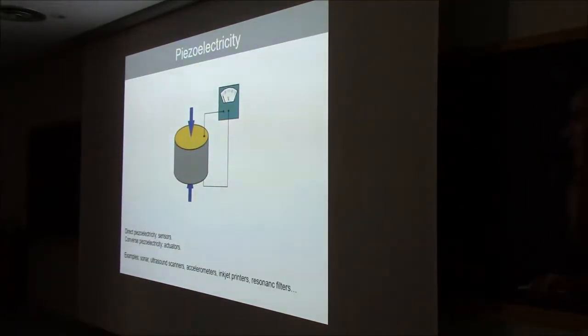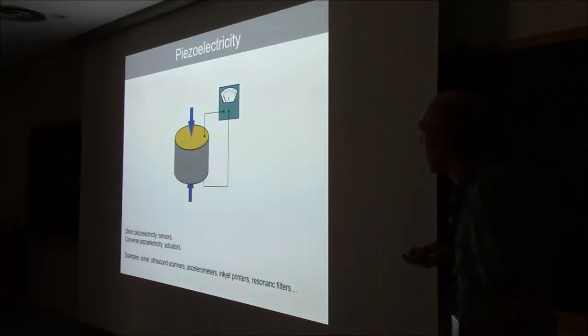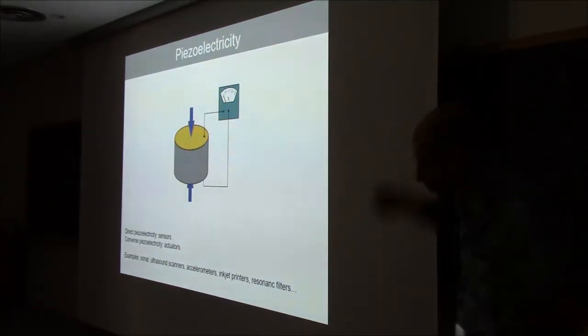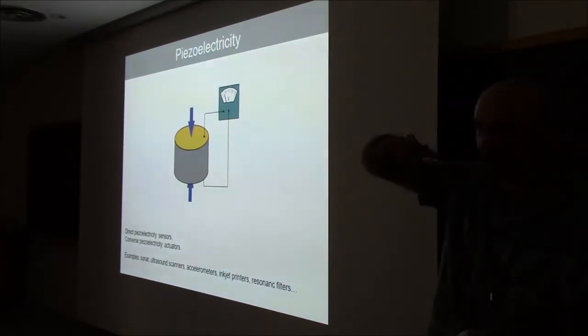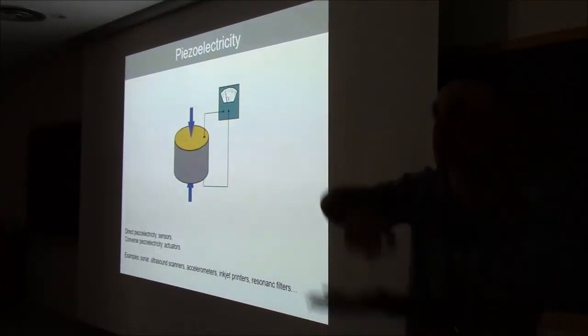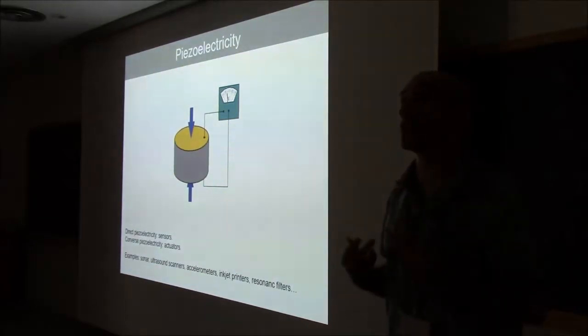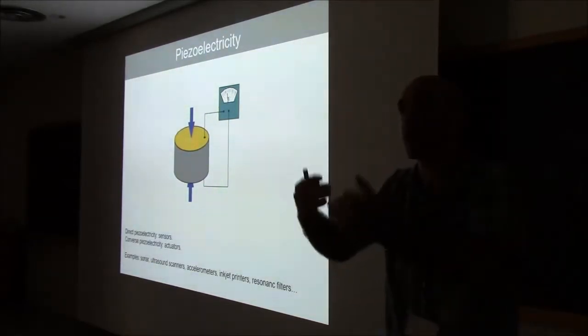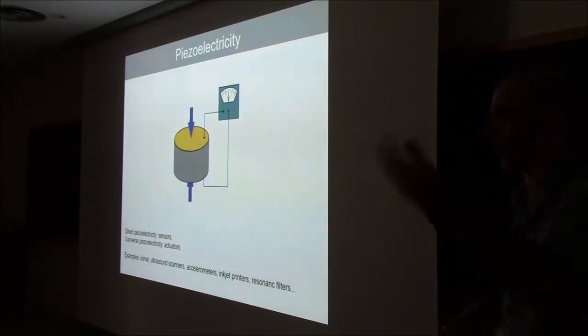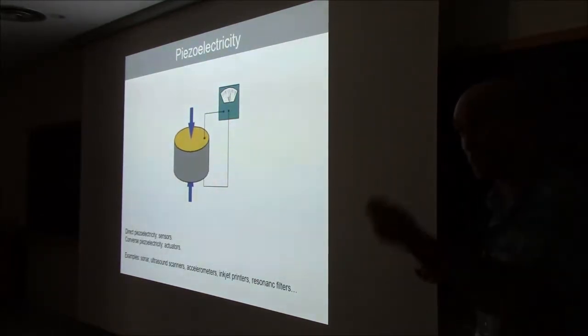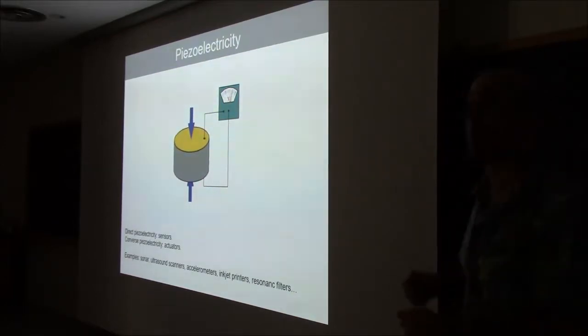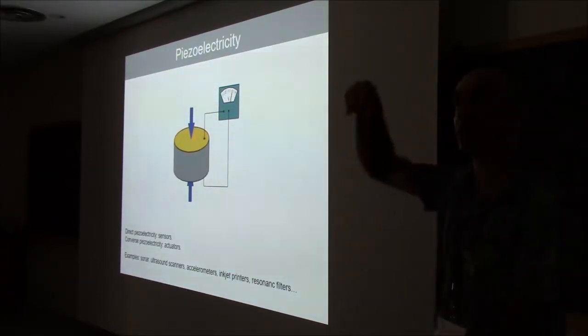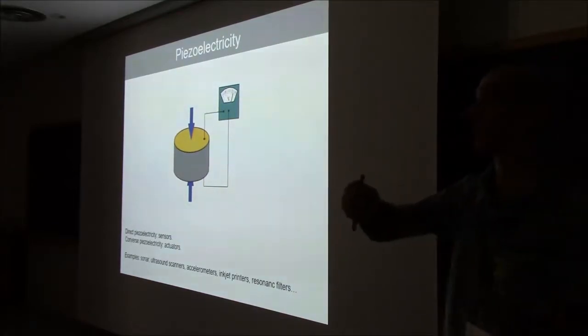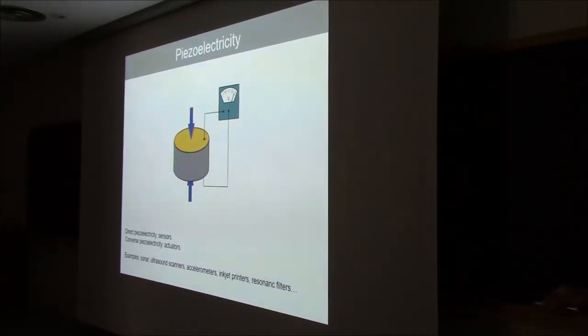So, this is piezoelectricity. You probably knew about this already. If you take a piezoelectric material and you push it, you change the shape of the unit cell. That changes the polarization, and when you change the polarization, you get a voltage. Okay? You generate some bound charge that will give you a voltage. I will talk in a second about what I mean by bound charge. Or vice versa, I can apply a voltage, and my material will respond by deforming in the direction of the electric field that I applied. And this is, again, super useful for sensors, for pressure sensors, and for actuators.